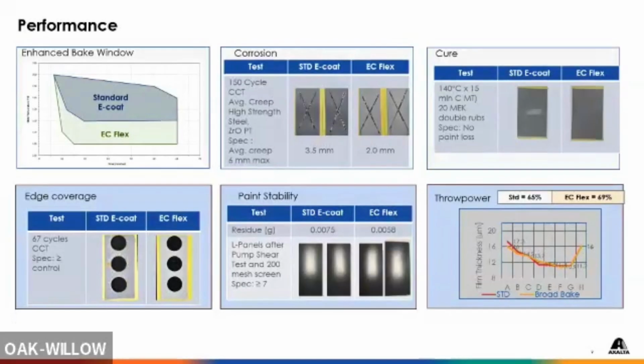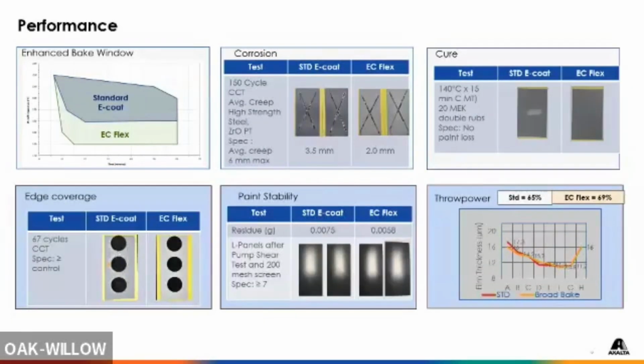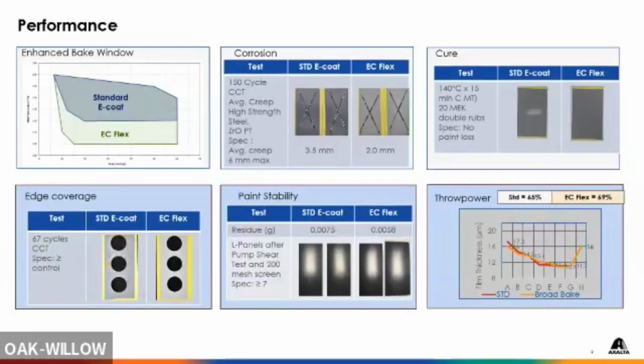In the middle, another thing that's very important is paint stability. So the middle one is basically the process of heat stressing the paint, seeing if some of that polymer falls out. Remember, Ecoat is a unique thing, right? We build the polymer in an oil-based system, and then we add acid groups and we trick it to go through a process which we call inversion, where we invert it into a water base, and then we can use it to run electrophoresis and deposition. But when you first start off on the Ecoat system, it is polymer synthesis in oil base, right? And then we trick it to go into water base.